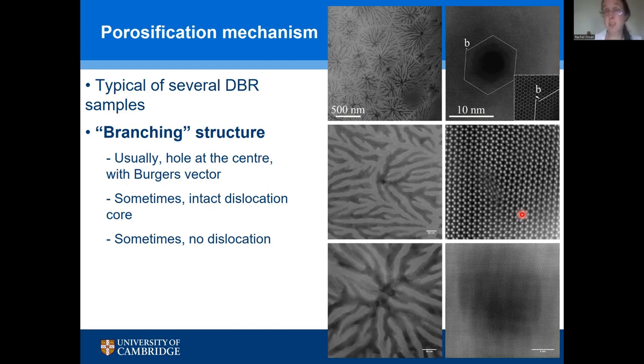I'm not sure about in the phosphides, but I'm pretty sure it's applicable to the phosphides. I just can't bring a paper to mind. So in terms of the original method, where you would etch a trench and then have the electrochemical porosification heading laterally, I'm pretty sure that's applicable to any material you happen to try it in. In terms of what we're doing about working down the defects, initially I didn't necessarily think of it for the arsenides, because you think of the arsenides as being a much more perfect material with very few defects. But for the samples that are grown on silicon, they actually do have threading dislocations, very much like gallium nitride, and people spend a lot of heartache trying to control those dislocations or get rid of them. And it is possible, although I haven't proved it, that the same mechanism would be applicable there.